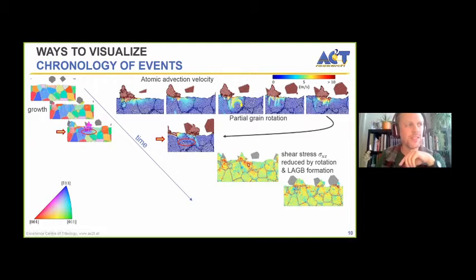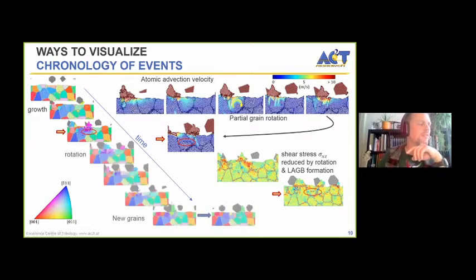And here you also see that in that particular grain, just before the lattice rotation, there was a high amount of stress, and then it rotated, the low angle grain boundary formed, and the stress was relieved. So then you can follow the system a little further. I'm not going to go through all the details. That's basically her field. But you can see that low angle grain boundary becomes a higher angle grain boundary and so on. And then the grain refines even further. So at the end, we have several small grains where before we had basically one.